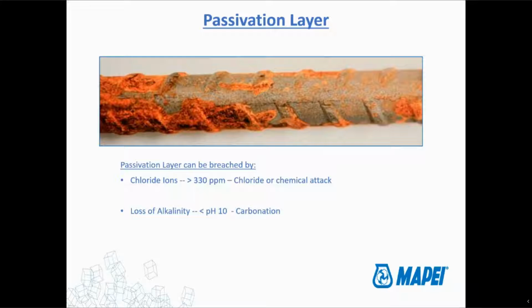So as you get more and more chlorides accumulating in your concrete, again, from that road salt, from the ocean spray, whatever it may be, those chlorides start to accumulate around the reinforcing steel. They want to react with that iron. The passivation layer works to protect the iron from reacting to an extent. But when you get above this chloride ion concentration, then the iron in the reinforcement steel is able to actually start reacting with the chlorides. Once that happens, then of course corrosion starts to occur, and we start to see the cracking and the spalling and the rusting and all the other problems that we associate with corrosion of reinforcing steel.